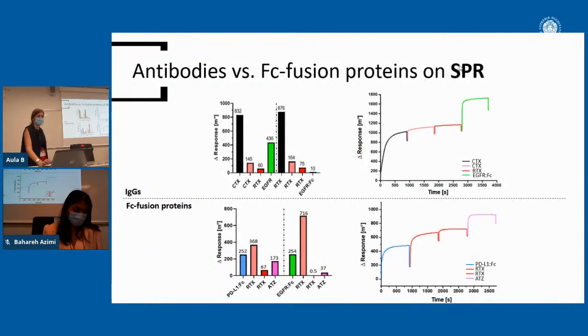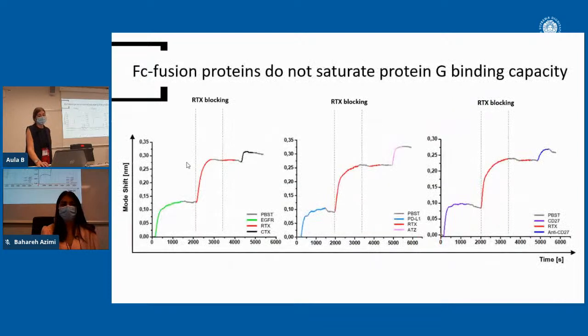So in order to check that this was not due to our setting, we performed the same experiments on an SPR platform, and we got the same conclusion. The IgGs can saturate the protein G binding capacity, but fusion proteins cannot. And this is most probably due to steric hindrance problems in the protein G Fc fragment interaction. However, looking at our data, we thought, maybe we can use this high rituximab binding as an advantage instead of a limitation.